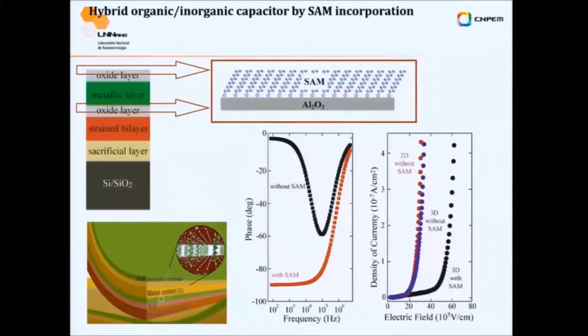You can see here, first, the phase as a function of frequency. When you don't have a self-assembled monolayer, it's basically leaky, or resistive. Oh, sorry, here is leaky. You can see almost zero. But when you add the self-assembled monolayer, you recover the capacitive behavior of your system. So here we show the comparison of the current density as a function of the electric field. After you include the self-assembled monolayer, you manage to extend the operation voltage, or the electric field you apply, almost twice.